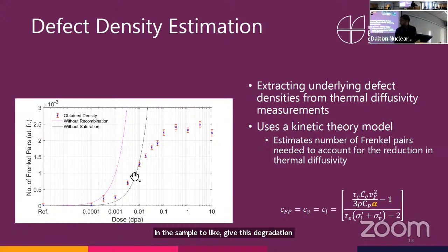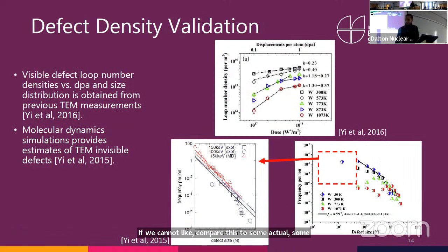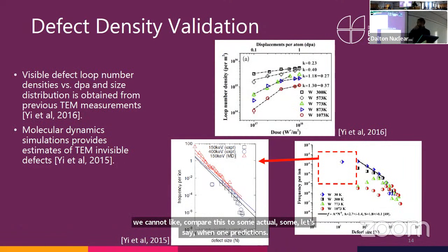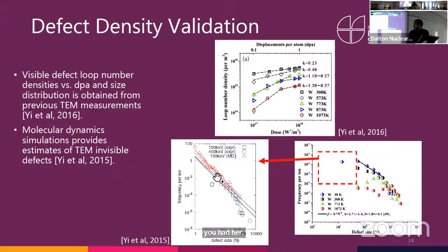And this was basically the prediction in terms of, say, Frenkel pairs. You had a Frenkel pair density of around 0.2%, and the black plot is if there was no saturation, and obviously the one in violet magenta is what you would have if there was no recombination, just Y = X, just for comparison. But this is all of no use if we cannot compare it to some well-known predictions. So that's why I dug up some of Xiao Yi's work, and she had her tungsten TEM work and molecular dynamics work.